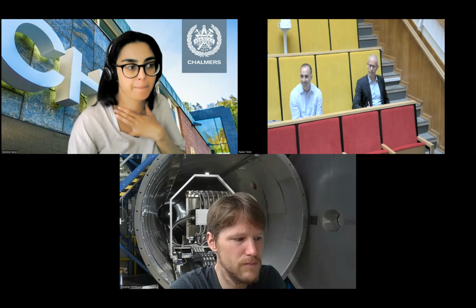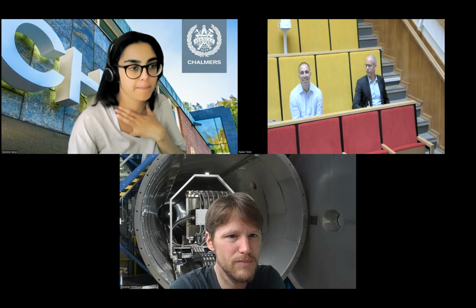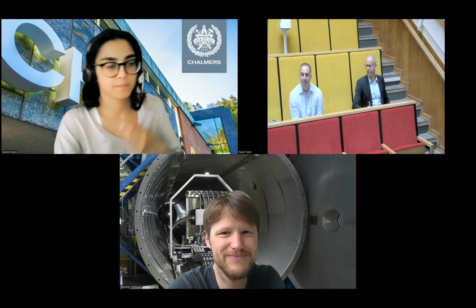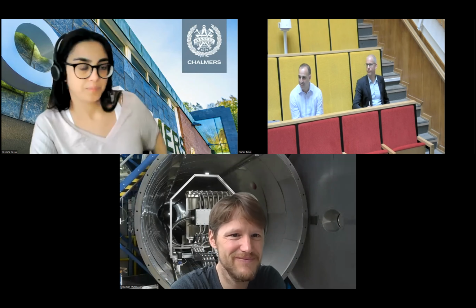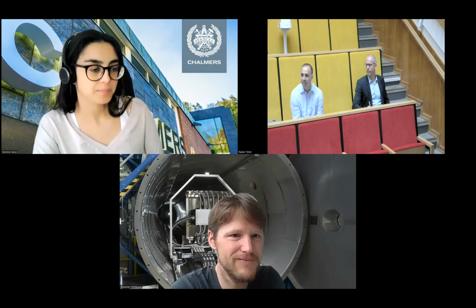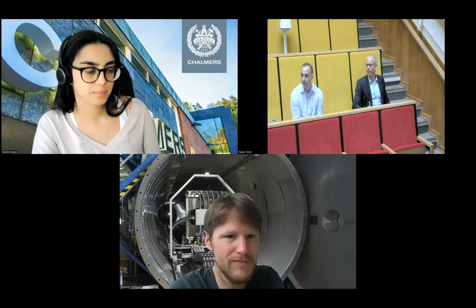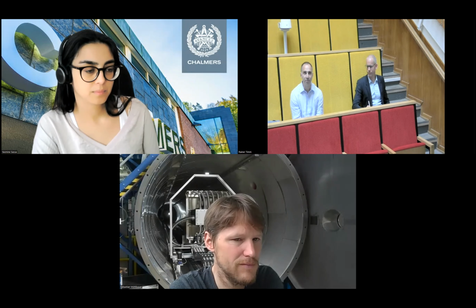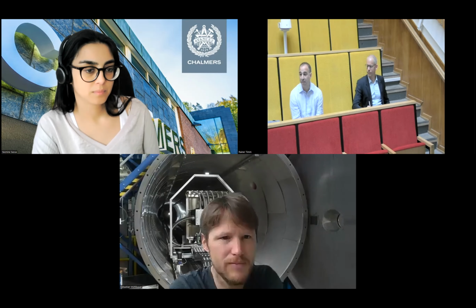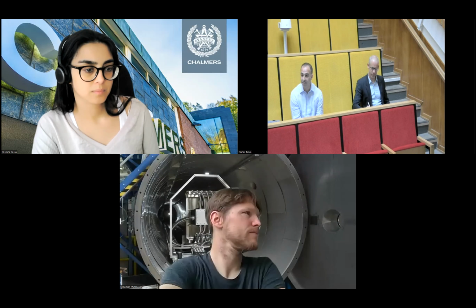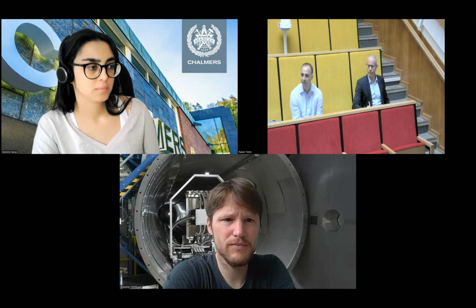Instruments surrounding the actual instrument that may affect, like spin echo measurements. Basically, my question is about the magnetic form factor. And the magnetic form factor decays quite rapidly with. So this means that even if you have this perfect instrument, you probably will not be able to see it. So what you will need in addition to that is a much longer wavelength. So still the angle is small.